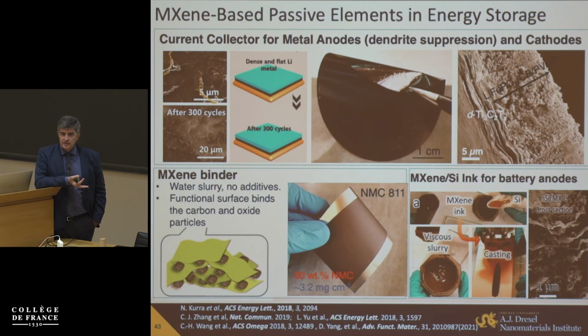Titanium-3 carbide-2 MXene is 2 to 3 orders of magnitude more conducting than activated carbon. So actually it can make faster electrodes, but also it eliminates polymer binder. So you can make electrodes without polymer binders, and currently with NMC we can actually go down to just 3% of MXene and still have a nice cohesive electrode when using it as a binder.